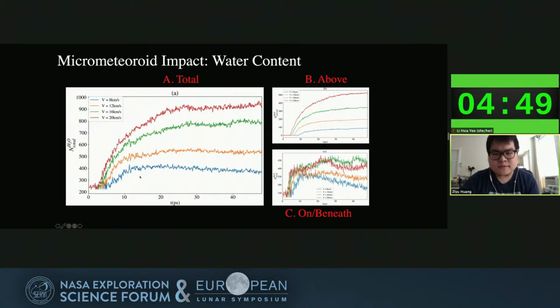We tested 4 different velocities ranging from 8 km per second to 20 km per second. The velocities are all perpendicular to the surface, and we will definitely include the effect of impact angle in the future. The left figure is the total water molecules, and on the top right is the number of water molecules above the surface, and the bottom right is for those on or beneath the surface. And we found that in total, micrometeoroid impact always produces more water by providing energy to hydroxyl groups for recombinative desorption. But at the same time, if you look at figure C over here, the retention of water molecules at